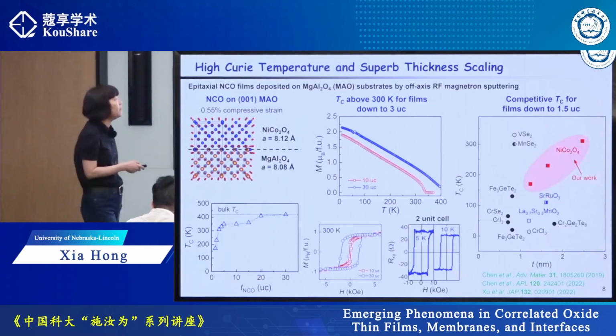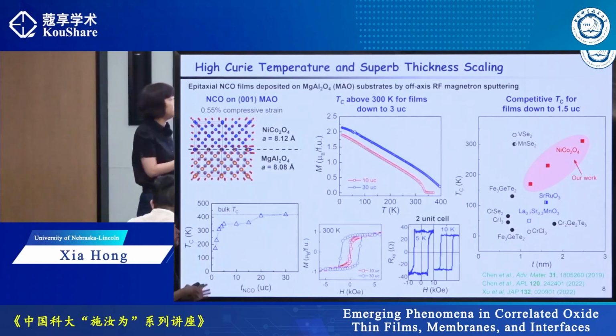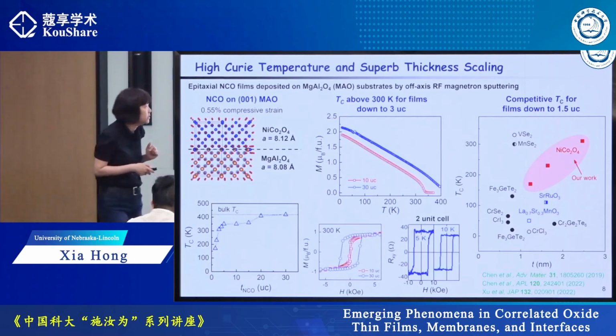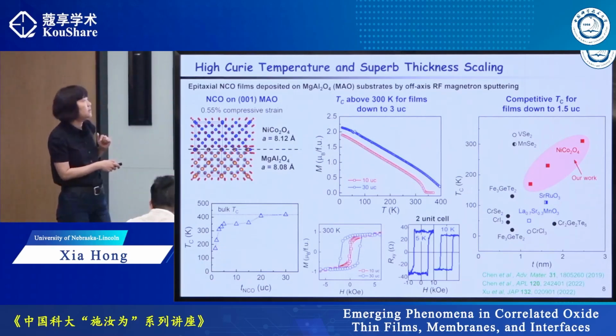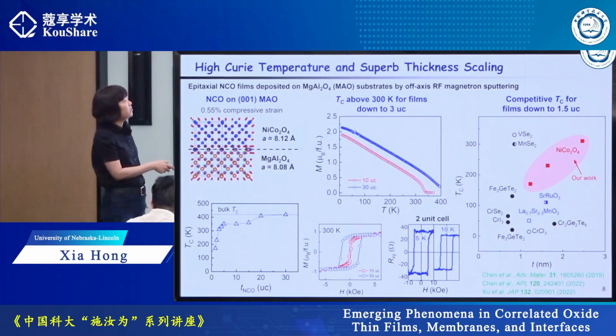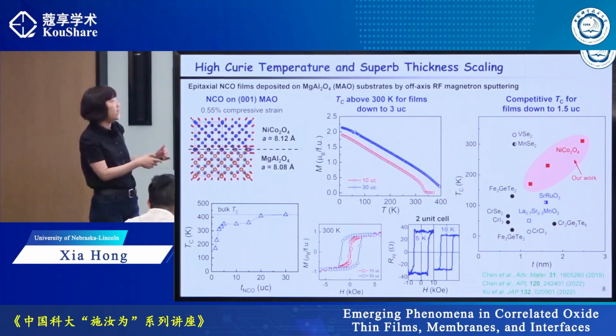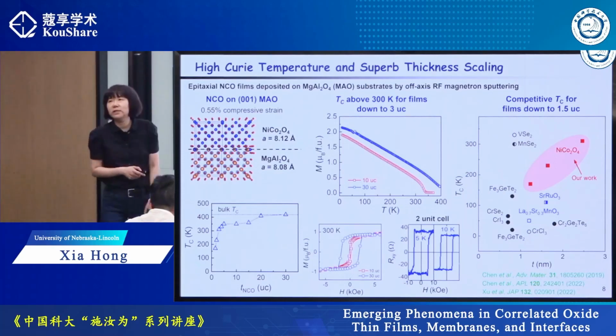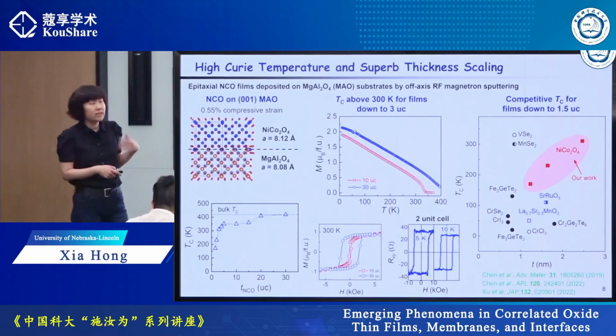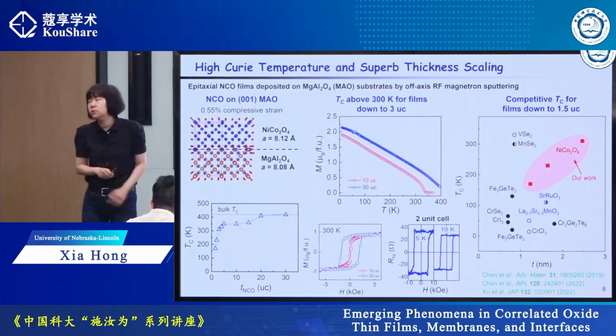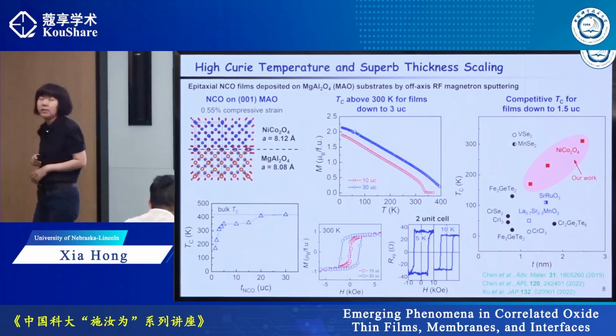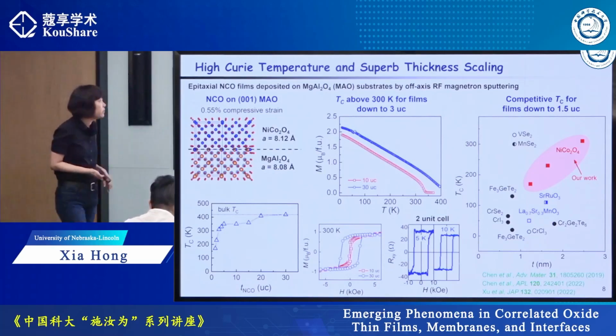And if you compare the magnetic property of NCO with other magnetic nanomaterials, here shows the plot of Curie temperature as a function of flake thickness. And NCO, its Curie temperature can actually be much higher than other correlated materials such as ruthenate and manganite. And it is also highly competitive when it is compared with other magnetic 2D materials.